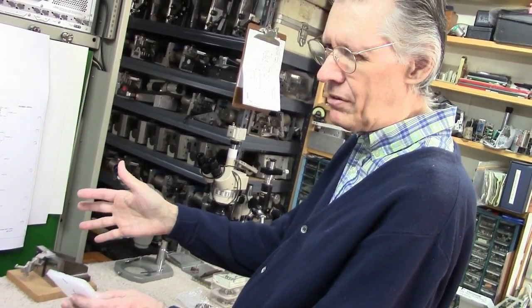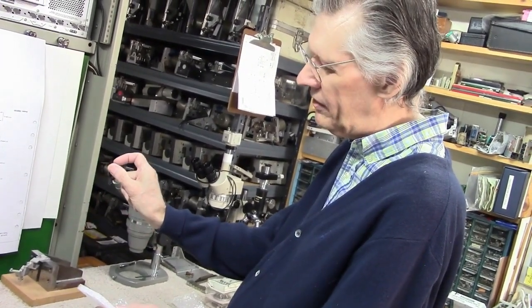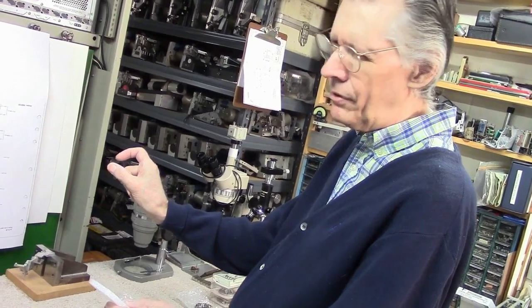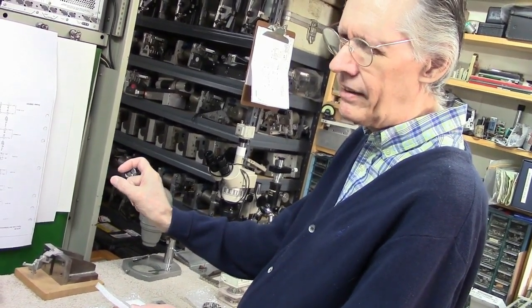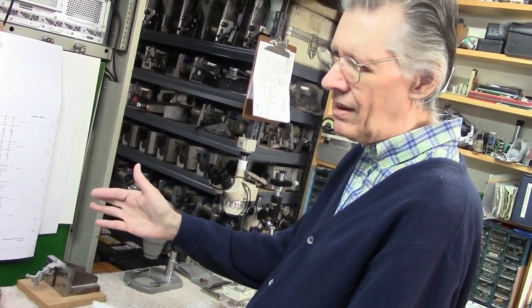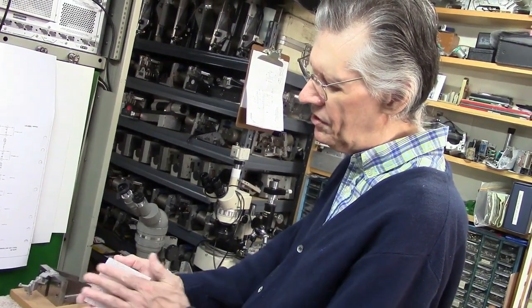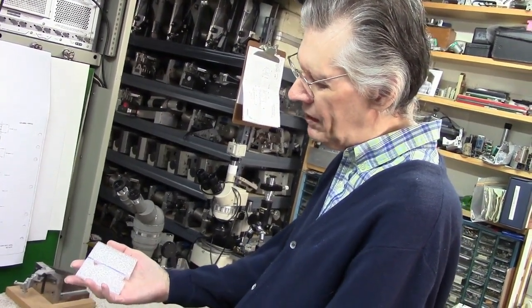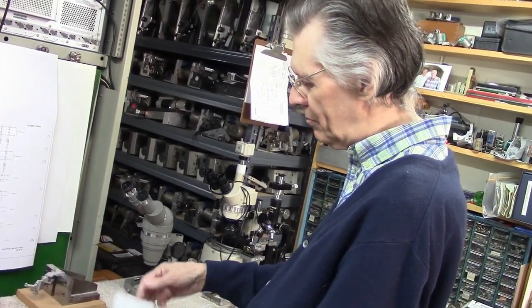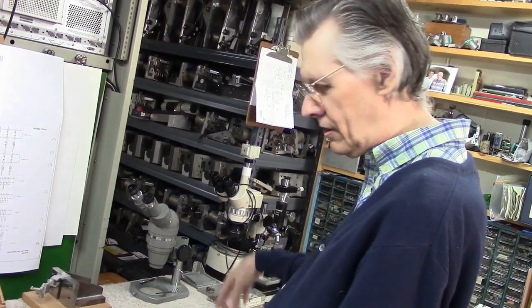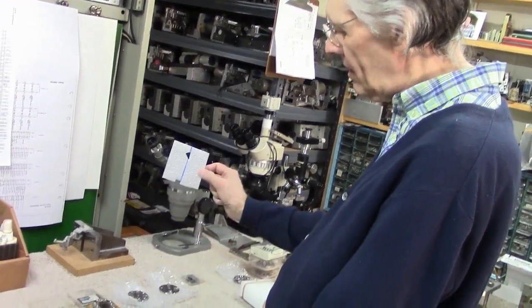And that accomplishes two things. That gets you down to the thickness you need, the track thickness of 10 mils. And it also polishes these sides to a mirror finish. And so you wind up, after you do all that, with a tip.